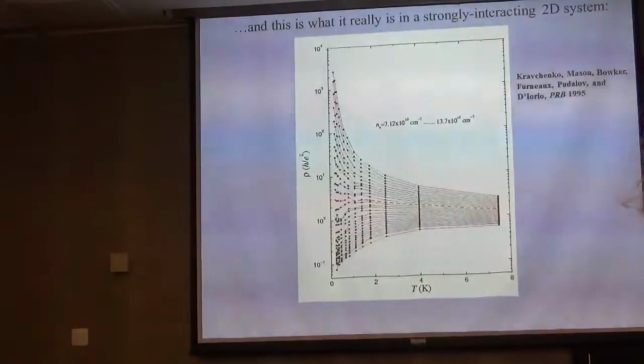So again, we have the lowest electron density and the highest electron density, but actually the highest and lowest are not so different from each other. It's a difference of less than a factor of 2. And again, I plot log of resistance as a function of temperature. If we have strong disorder and few electrons, we have localization, right? We go down in temperature, and the resistance grows by many orders of magnitude. That's what it's supposed to do.